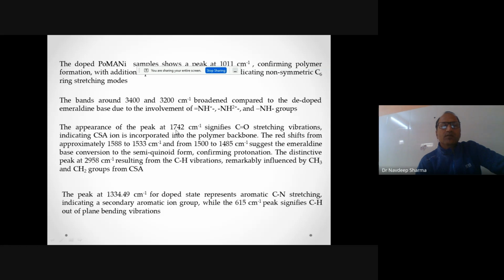The appearance of the peak at 1742 wavenumber signifies carbon-oxygen stretching vibrations, indicating the CSA ion is incorporated in the polymer backbone. The red shift from approximately 1588 to 1533 and from 1500 to 1485 suggests the emeraldine base conversion, that is, the emeraldine conducting state to the semiquinone form, confirming the protonation which is responsible for the conductivity in the polymer. The distinctive peak at 2958 results from CH vibrations, remarkably influenced by CH3 and CH2 groups from the camphor sulfonic acid dopant.